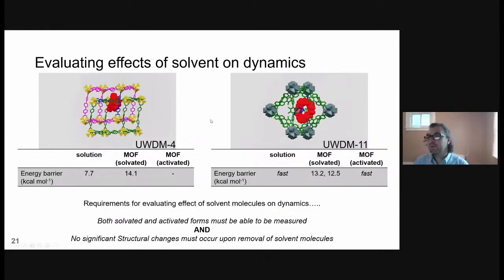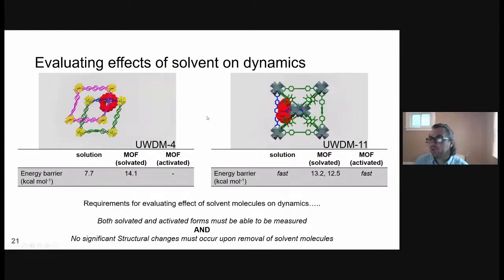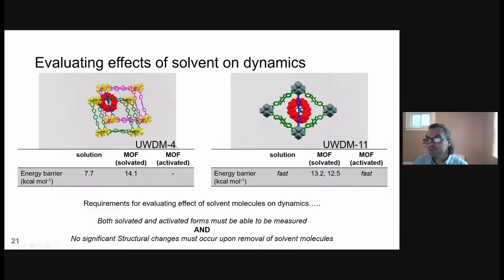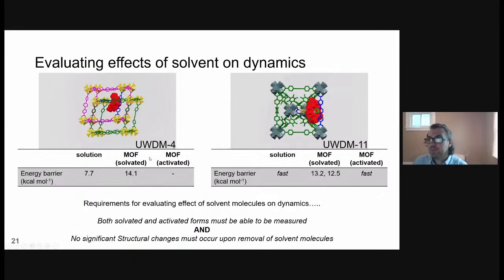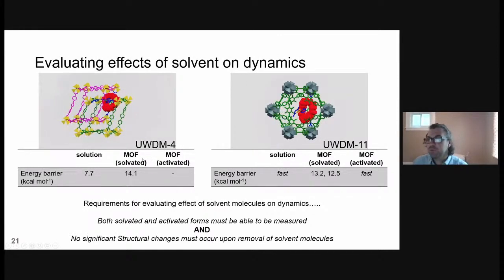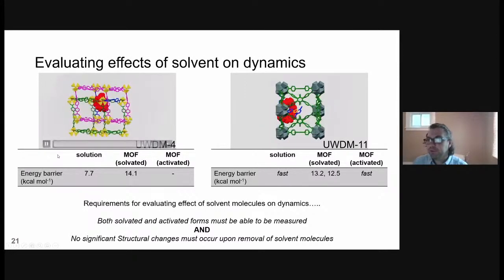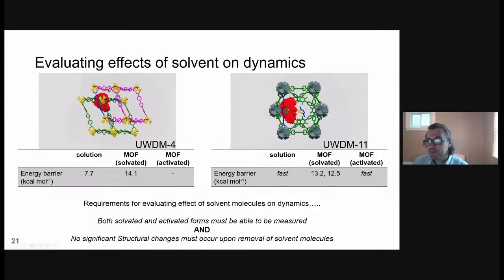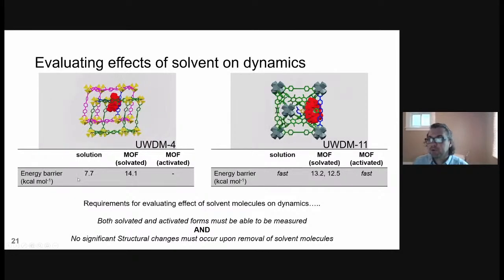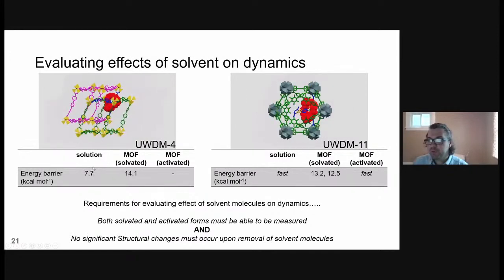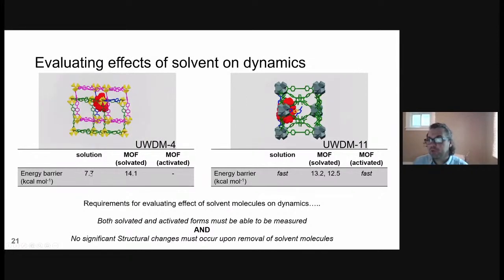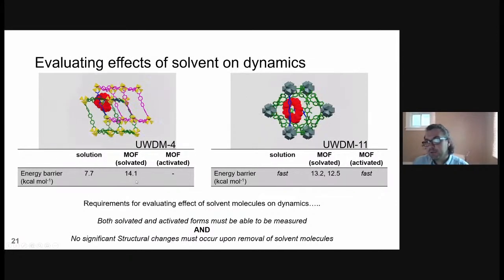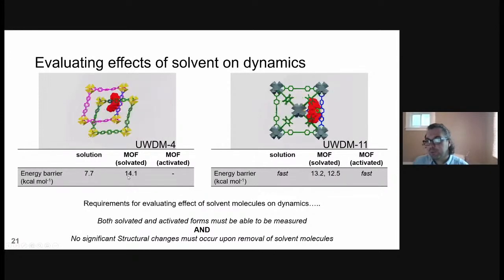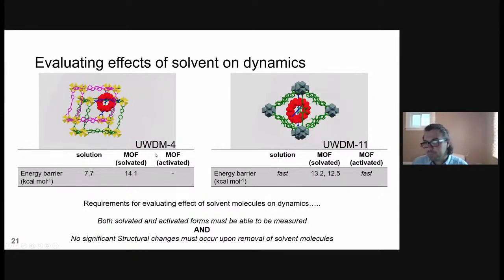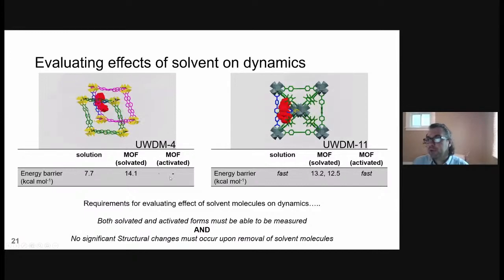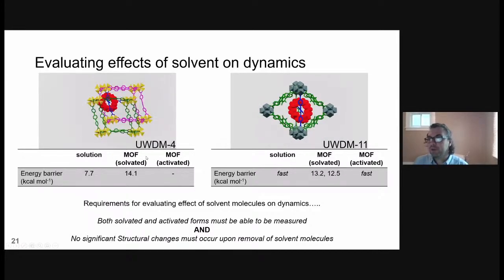So in terms of evaluating the exact effect of solvent on dynamics, if we first start with UWDM4, which I mentioned right at the start of this presentation, was the first example of one of these molecular shuttle type systems. We're able to measure the energy barrier in solution for this translational motion was 7.7, and then when we measured the solvated MOF, it was almost double at 14.1. However, unfortunately, we weren't able to measure the activated form as the framework collapsed.